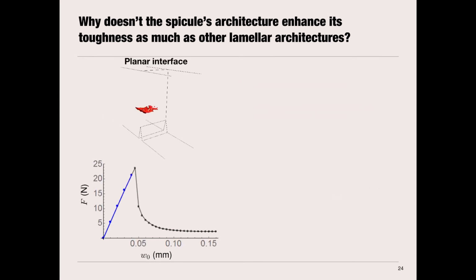For the planar system, you can see the crack growth shown in red as the damage field on the top, and on the bottom we have our force displacement response. You can see a jump in the force displacement response, much like you'd see in nacre or even the architectures that Dr. Yin just presented. This jump corresponds to crack arrest at the interface, or a Cook-Gordon mechanism, if you're familiar with that, as well as it being accompanied by some deflection. But the deflection at the interface doesn't actually dissipate that much energy because the toughness of the interface is so much lower.